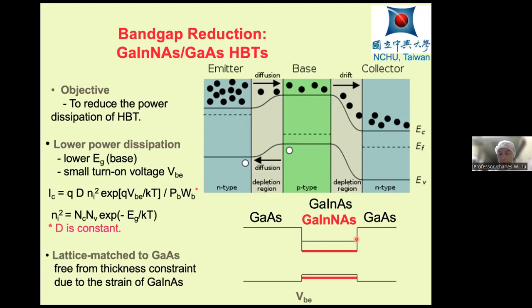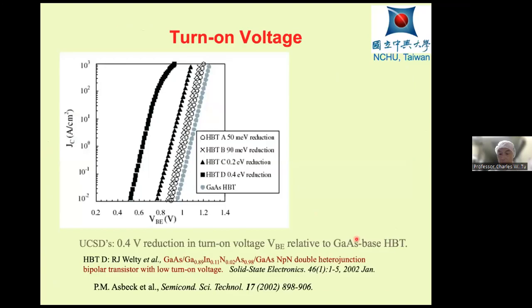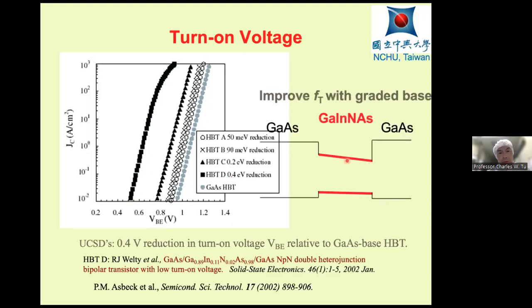But here is a result. We see the collector current, and this gray line is for the gallium arsenide HBT. And then we put nitrogen into the base, and you see that we reduce the base-emitter voltage, by like 0.4 volts. Here we also grade the base to improve the electron transport, but that's beside the point.